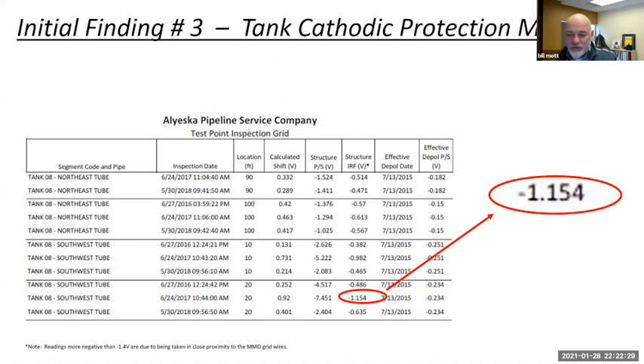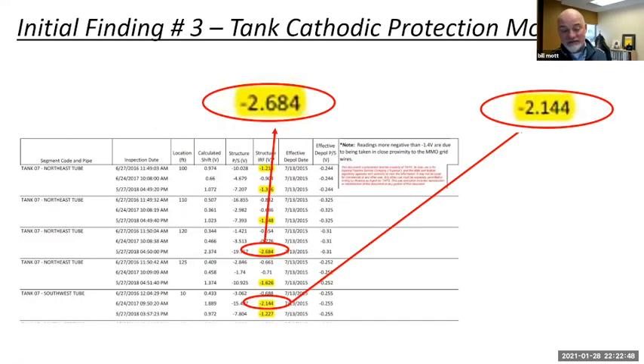This is pulling out some of their instant off data. It's not terribly negative. It's more negative than what NACE suggests would be reasonable. It's negative enough that it should have thrown a flag to the operator to take a second look and dig into things a little bit more. I looked at the tank in the very same tank cell, tank 7. It's adjacent to tank 8. It's monitored by the same personnel using the same techniques and the same procedures, and they're reporting IR-free data of up to 2.7 volts. This is just an excerpt, and these are up in that neighborhood.